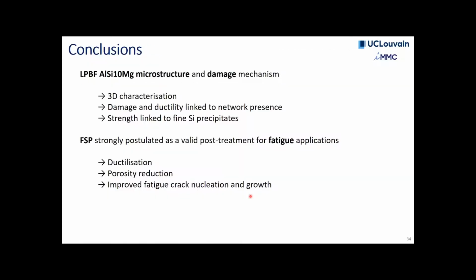So this brings me to my conclusions. I've shown you a bit about L-PBF microstructure and damage mechanism. We've done some nice 3D characterization of the silicon networks. Damage and ductility is linked to the presence of this network, and the strength is linked to the fine silicon precipitates. I've just shown you that very shortly, but I haven't proven that with results. And friction stir processing is strongly postulated as a valid post-treatment for fatigue applications, including the impressive ductilisation that you have going from 0.1 to 0.4 true strain at failure.